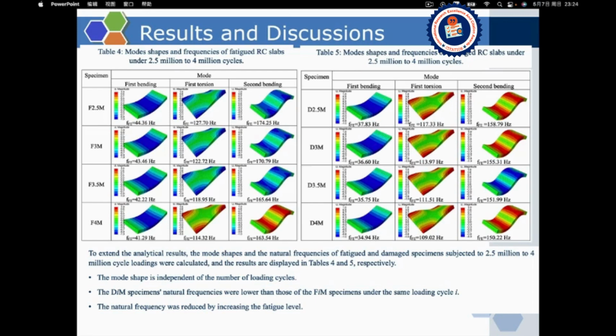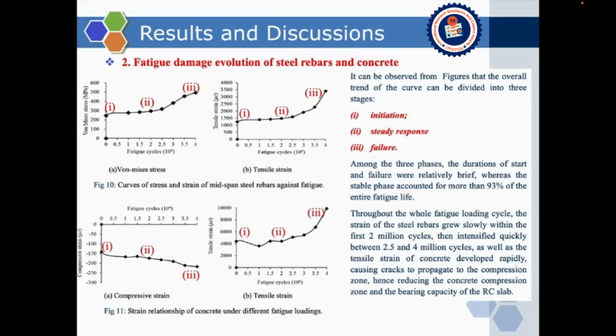Finally, we extend the analytical results from 2.5 million to 4 million loading cycles. The results show the same variation as those subject to smaller loading cycles. Hence, the mode shape is independent of the number of loading cycles. Under the same loading cycle, the damaged slab's natural frequency was lower than those of F/M specimens. Besides, the natural frequency was reduced by increasing the fatigue level.